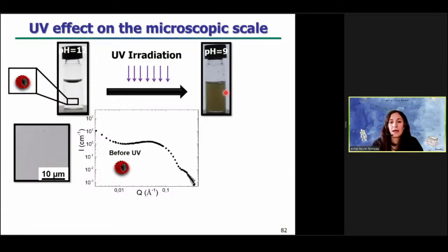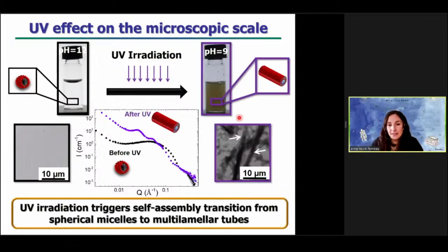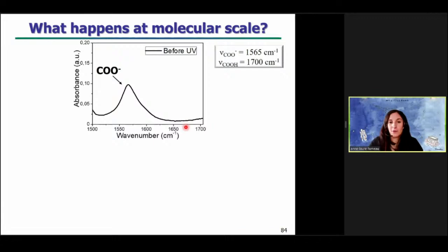And then by TEM, what we can see is the presence of micron-sized tubes, and by small angle neutron scattering, we can clearly see on the scattering curve the Bragg peaks that I showed you in the first part of my talk. So we recover these big micron-sized multilamellar tubes. So it's really the UV radiation that triggers the self-assembly transition from the spherical micelles, in this case, to the multilamellar tubes. But we wanted to understand what is happening at the molecular scale that can lead to this transition at the supramolecular scale upon UV radiation.